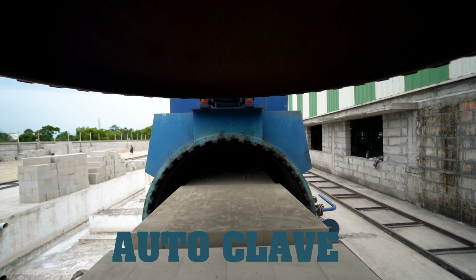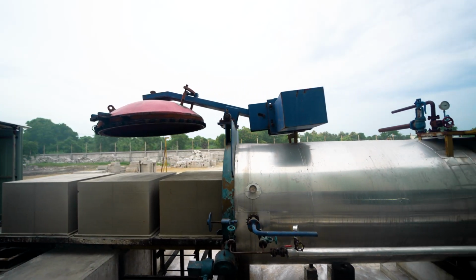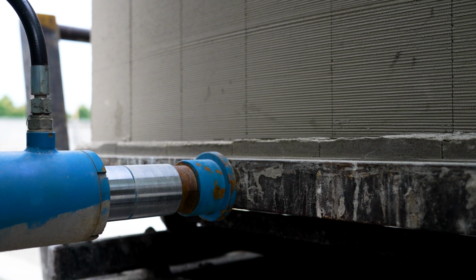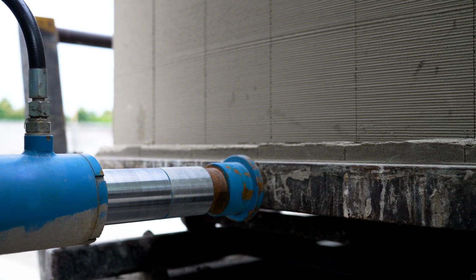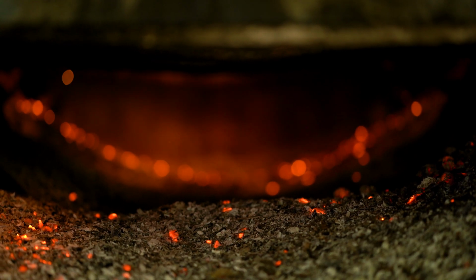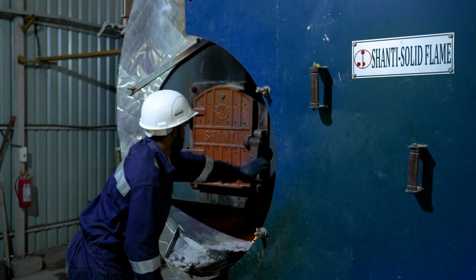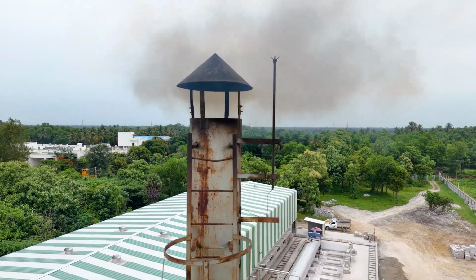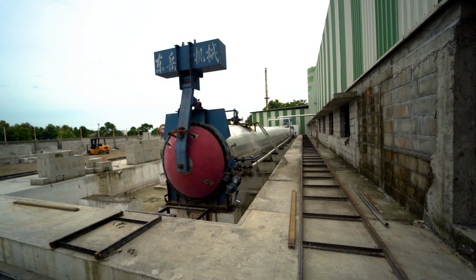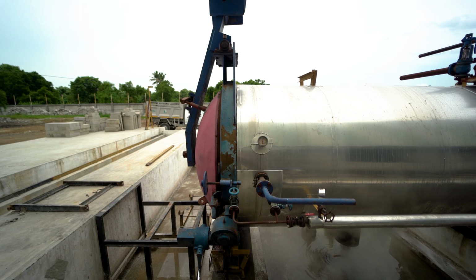Autoclaving. To cure the blocks under high pressure and temperature, enhancing their strength and durability. Loading into autoclave. The cut blocks are placed on curing trolleys and loaded into an autoclave chamber. The autoclave is sealed and steam is introduced at high pressure, 8 to 12 bars, and temperatures of 180 to 200 degrees Celsius. The steam curing process typically lasts for 10 to 12 hours.